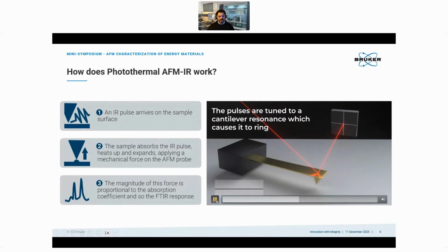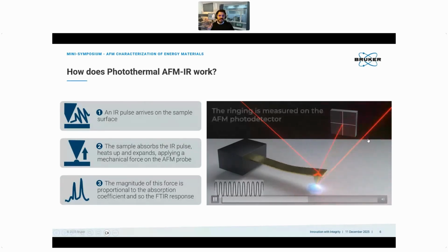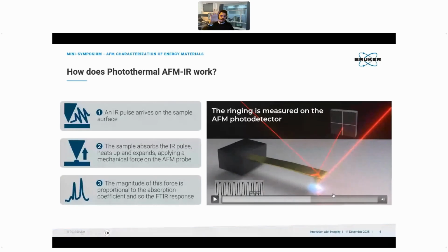However, this expansion is pretty small. It could be a few picometers. So we need to enhance the signal that we can measure. To do that, we use the so-called contact resonance approach, which means that instead of sending the infrared laser to the surface statically, we send it as a pulse. So basically what you see here is the laser pulsed into the surface. It's on, off, on, off.